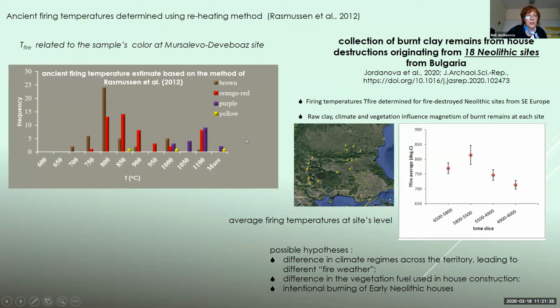Here again, you can see that the firing temperatures also are related to the prevailing color of the material. The firing temperatures ranged between 700 to higher than 1000 degrees centigrade. And the highest temperatures were obtained in purple melted material. So this result inspired us to look for other Neolithic sites and to look for similar phenomenon, we studied remains from 18 Neolithic sites from Bulgaria,